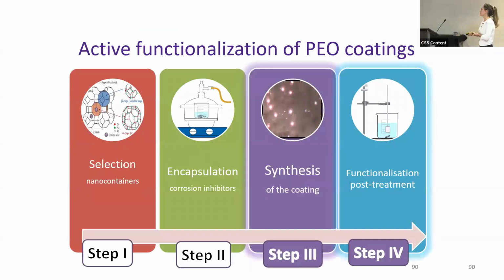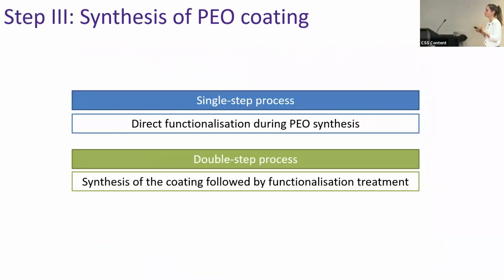The next step of the process is the synthesis of the coating and the functionalization post-treatment. Here we have 2 possibilities. We can try to do these 2 steps at once in a single step, or we can do them separately in a double-step process. The single-step process is a little bit more challenging, but it's also faster.